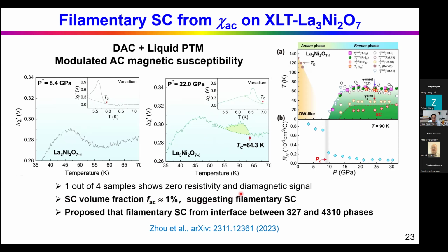So it suggests it's a filamentary superconductivity. And according to this recent update, they propose that the filamentary superconductivity actually comes from the interface between the 327 and the 4310 phases. It's not bulk, it's high TC superconductivity. So that's why there's still debate on whether we can achieve bulk superconductivity or not in this 327 phase.